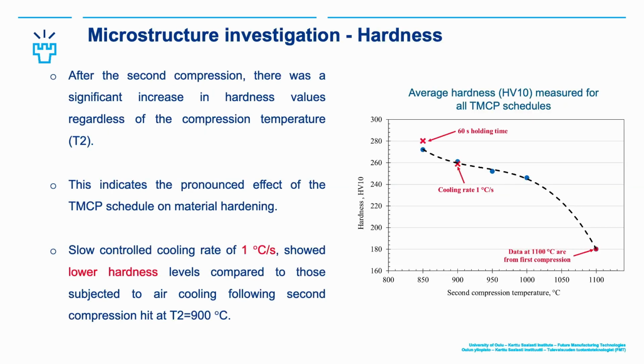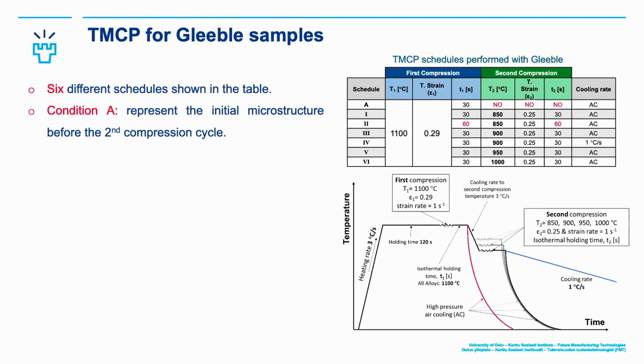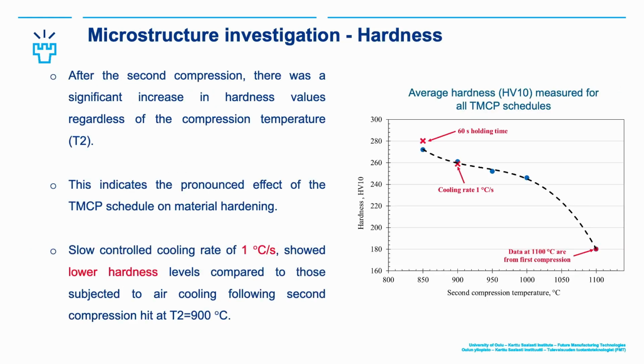Moving to the results from the TMCP samples. These are the hardness measurements, and this point is the first compression, so this is point A. We could see that in all of the schedules from the second hit, we have increased hardness. There was one schedule, I'm sorry, I forgot to mention: at this point we have one very slow cooling, a controlled cooling of 1 degree Celsius per second. This is also an important point. At the same temperature of 900, we have 2 points, one which is slowly cooled, and one which is almost air quenched. And this is the one with the holding time.